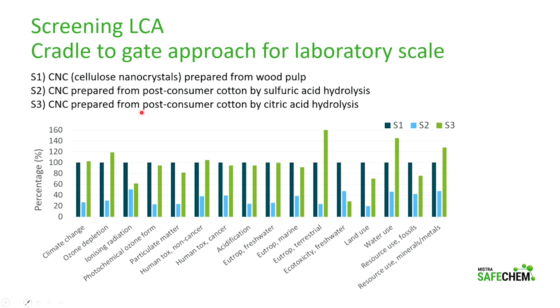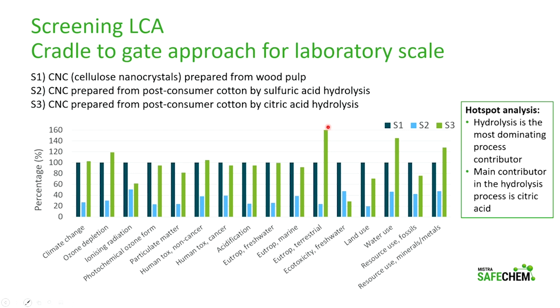So we could see that the processing of cellulose nanocrystal from post-consumer cotton by sulfuric acid hydrolysis, which is shown by the light blue color bars, is actually much more environmentally friendly than wood pulp as a resource. But when we come to the citric acid system, it is not the case. It is almost the same as the wood pulp. And you can easily see that eutrophication is one of the key hotspots in this screening LCA.